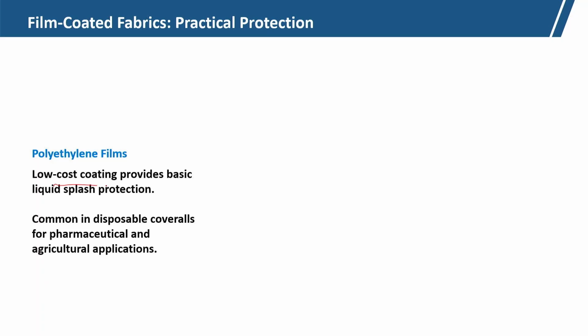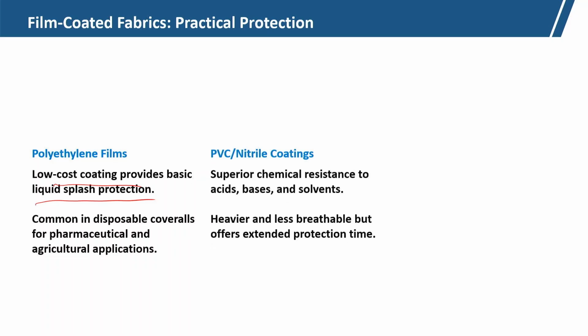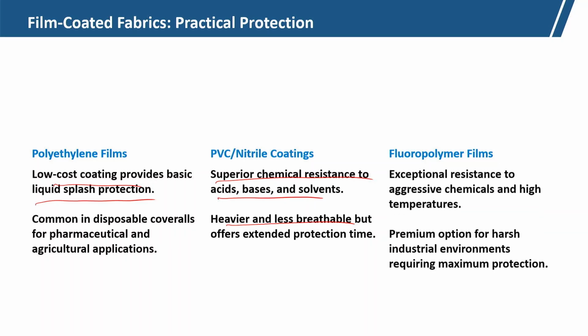which will be a low cost coating and provides basic liquid splash protection. PVC or nitrile coating we can use, with superior chemical resistance to acid, base or solvent. So, nitrile coatings are used, but it is heavier and less breathable because of the nitrile coating. And fluoropolymer coatings have exceptional resistance to aggressive chemicals and high temperature. So, for very aggressive chemicals we can use the fluoropolymer film.